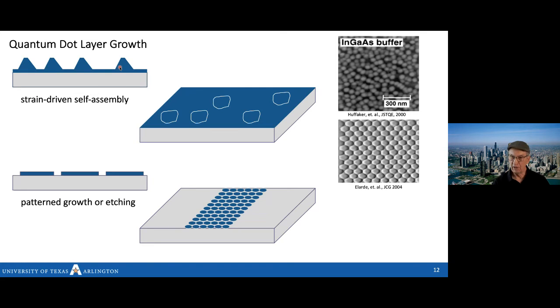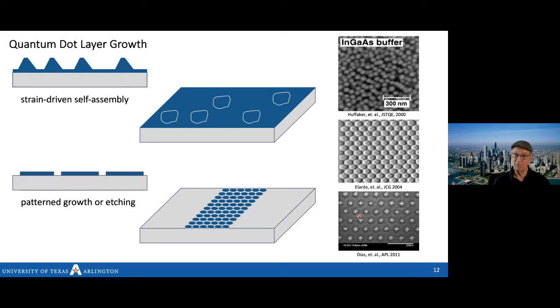And there's a picture of one of ours from 2004, and those are what the dots look like after you've etched away the oxide. And in fact, you can combine these two techniques and do both the strain driven and pattern, and we've done that. We basically put some holes in the oxide first and then grew the material in the holes using the same process in self-assembly. They're still self-assembled, but the diameter is sort of constrained by the size of the hole, and then the patterning is very regular.